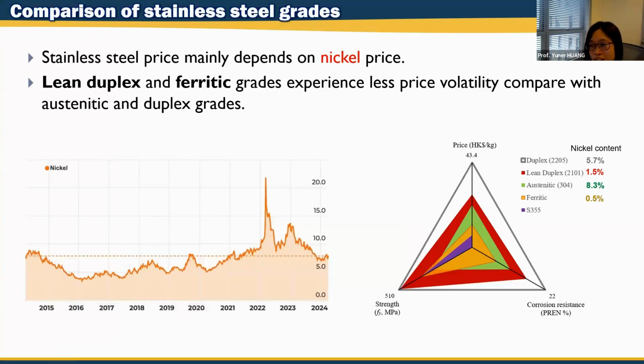Okay, so this slide is also important in terms of price, because as I mentioned, the stainless steel price mainly depends on the nickel price. And nickel is a mineral that fluctuates very much. So imagine that if you use lean duplex and ferritic stainless steel, these two stainless steels have a much lower nickel content compared with austenitic and duplex stainless steel. You can see lean duplex has only 1.5 nickel. Ferritic has 0.5 nickel, compared with austenitic and duplex, which have much higher nickel.